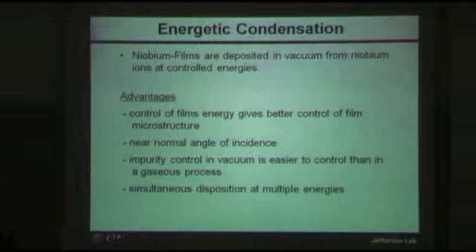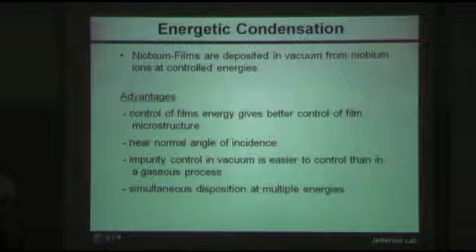The advantages are that the added energy produces a much higher quality of film microstructure. The impact energy transferred to the lattice from each ion creates a local transient thermal spike, which helps the film atoms settle into the lowest energy sites, which gives a more ordered crystalline structure. And this is a basic mechanism.